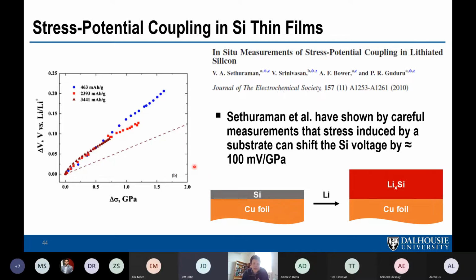And in thin films, the amount of shift as a function of the stress could be measured, and it's about 100 millivolts per gigapascal of shift.